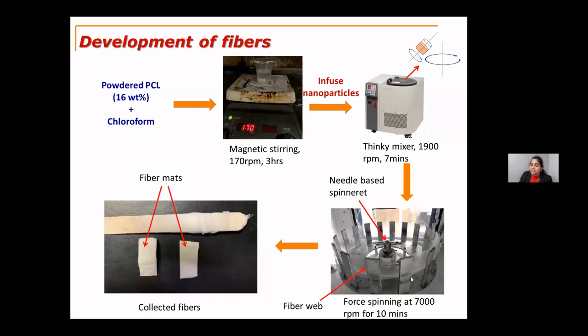I did a completely different study varying the speeds. I chose 5, 6, 7, 8, and 9 thousand RPM. For this hydroxyapatite nanoparticle, 7000 gave a better yield compared to the other speeds, and continuous and uniform fibers at 7000 RPM. So the first spinning was done at 7000 RPM for 10 minutes.